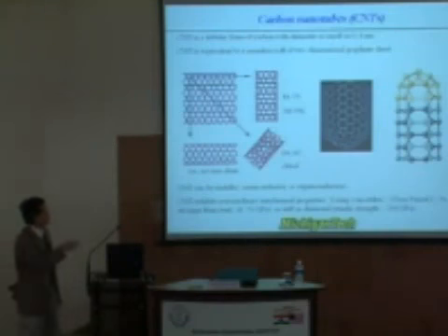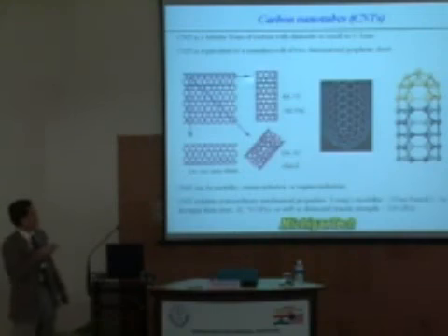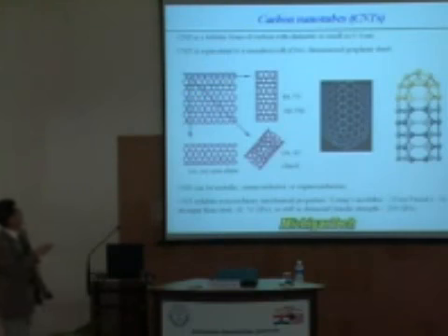Some of you are already familiar that you start by considering a piece of hexagonal network of carbon. It's just like a piece of paper, except that you have carbon at each junction, each carbon staying at one corner. You fold this graphene sheet so that the edges fit into these edges here, and you will form a seamless cylinder. In this case, you call this a zigzag carbon nanotube. Or you might fit these edges, which are in a zigzag shape, to match this edge by folding it downward. Then you form nanotubes called armchair nanotubes.